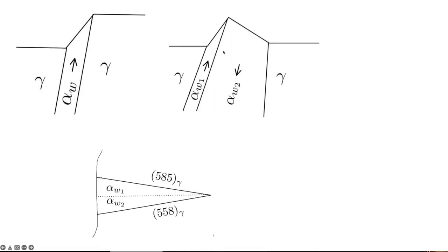So these two plates will not be in exactly the same crystallographic orientation, but we should be able to see a low misorientation boundary between the two plates. So they have different variants of the habit plane, 558 approximately and 585 approximately. And therefore, they must have different crystallography. It cannot be in exactly identical orientation. And indeed, when we do transmission electron microscopy, you can see in what appears optically to be a single, very coarse plate, is actually two fairly coarse plates with a low misorientation between the two sides.